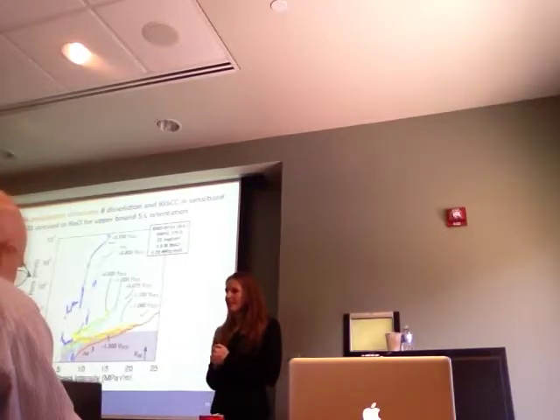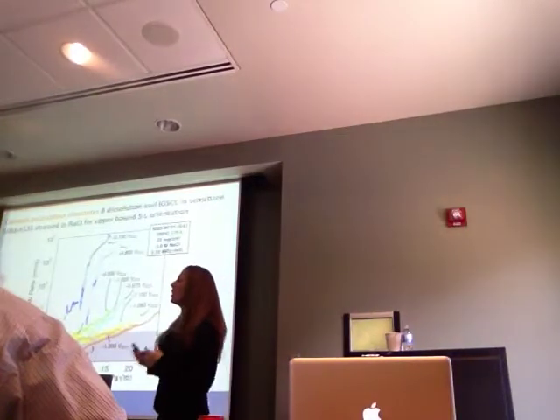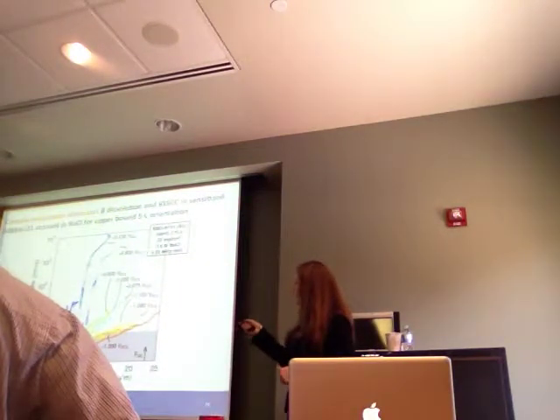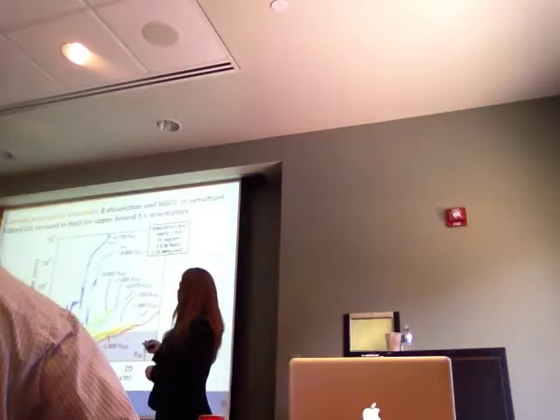So I looked at this experiment with several different polarizations at one sensitization level. And that sensitization was 100 degrees C for 175 hours, which is about a week. And that gives you a 22 milligrams per centimeter squared mass loss, what we looked at before. And the exact experiment that I showed you earlier is right here at negative 800 millivolts. And you can see when you anodically polarize, your crack growth rate increases and your threshold stress intensity decreases. So you're actually getting worse stress corrosion cracking when you anodically polarize.